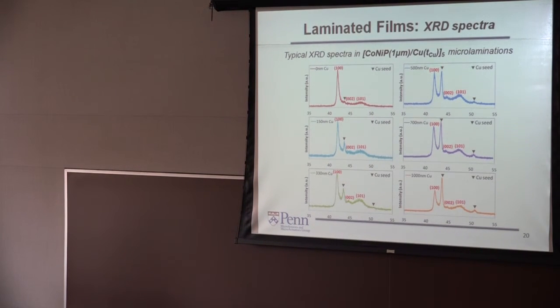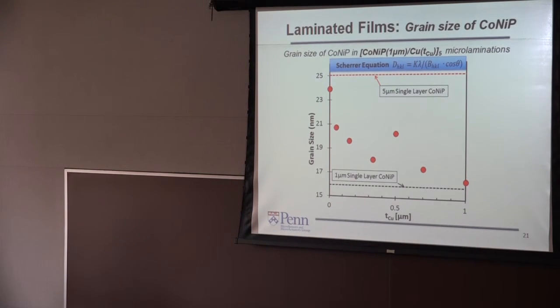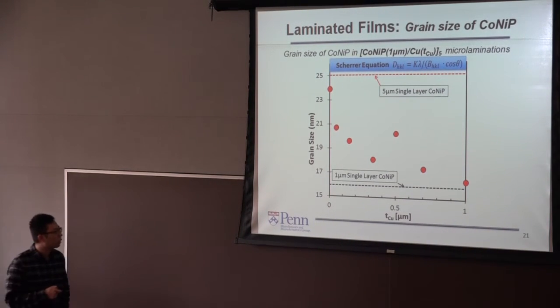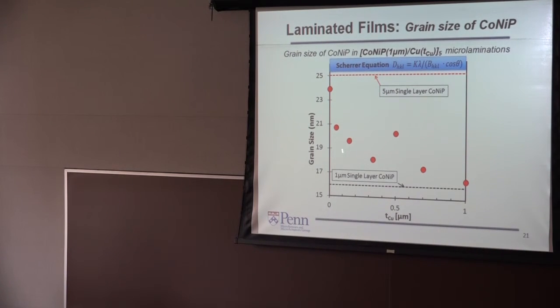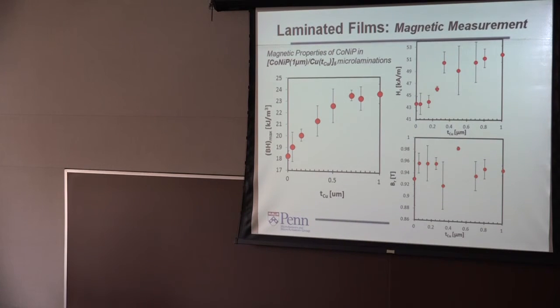We also did XRD on these laminated structures to compare with the single layered counterparts. By comparison, we found there are no additional or missing peaks for the cobalt nickel phosphorus, but there's one thing that changed. By analyzing the peak 100 using the Scherrer equation, we found that the grain size decreases as the interlayer thickness increases. This is very similar to the trend of the roughness, and it's also bound by two extreme cases, the 5 micron and 1 micron single layer case.